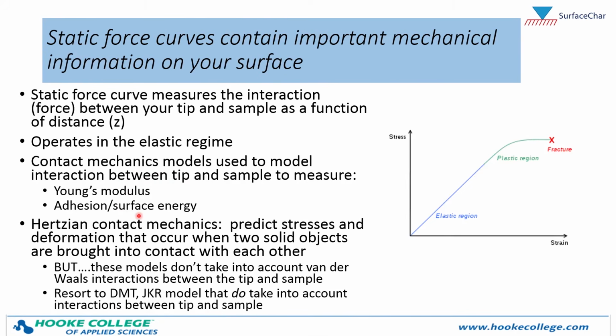Now, the building block model in the contact mechanics model is called Hertzian contact mechanics. Hertz predicted the stresses and deformations that occur when two solid objects are brought into contact with each other. I'm going to review it briefly on the next slide. He developed it in the 1880s, but it is important to note that this is just the building blocks for the contact mechanics models we use in AFM, because the problem with the Hertzian model is that it does not take into account van der Waals interactions that most certainly occur between the tip and sample in our AFM measurements because they're on the nanoscale. On such a small length scale, van der Waals and adhesion become forces that we have to consider. And so ultimately what we can resort to are these newer models called the DMT and JKR model that do take into account the interactions between the tip and the sample.